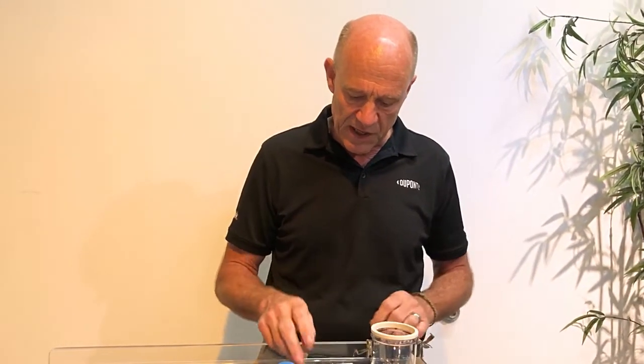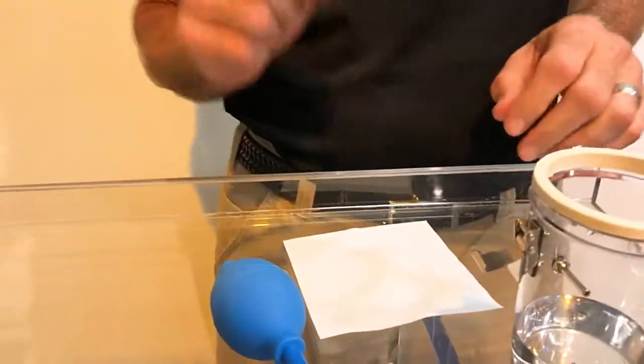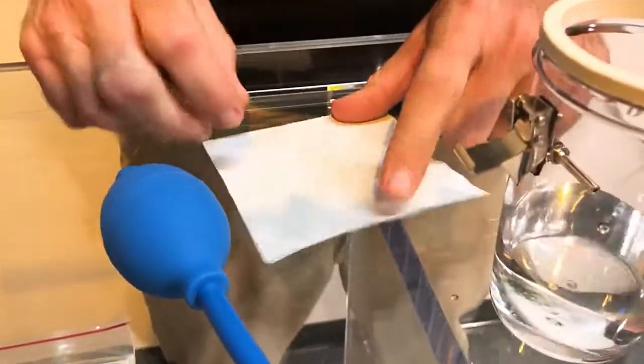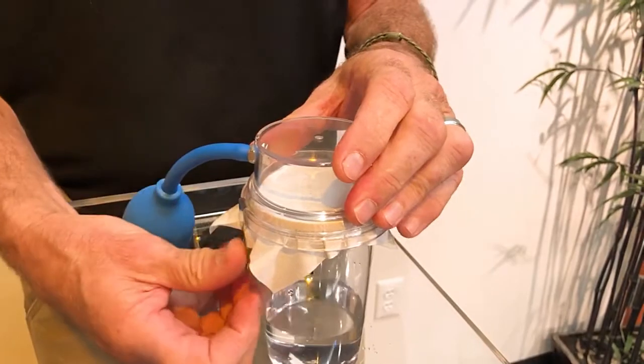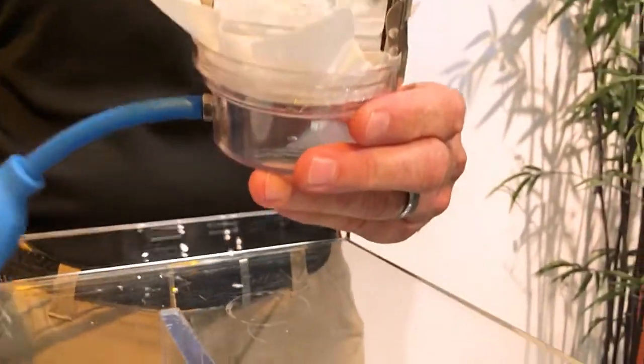One of the challenges with microporous film fabrics as PPE is that the protection this fabric has comes from that very thin layer of plastic. So if I take my fingernail, which isn't particularly sharp, and I try and scratch the surface of that material, and now I repeat that exact same test — I turn it over, I squeeze it — now it's highly breathable.